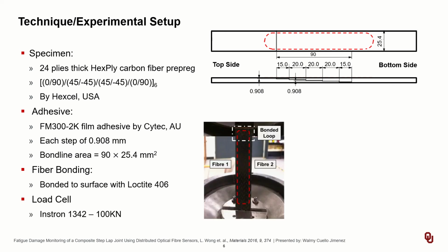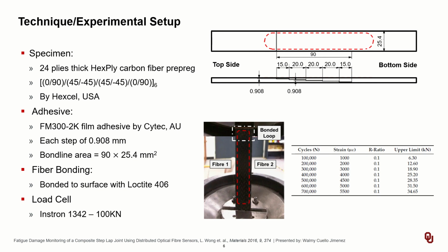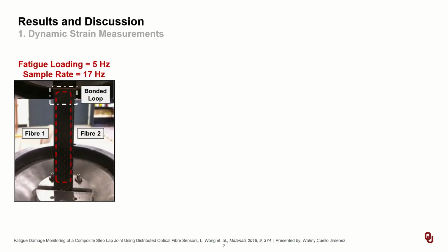component. And finally, the specimen is placed into a load cell with a capacity of 100 kilonewtons to perform the fatigue testing. As you can infer from the setup, the photo of the fiber was split into fiber 1 on the left and fiber 2 on the right for experimental purposes mainly. Now the fatigue testing is designed to increase by 1000 microstrain every 100,000 cycles with a minimum to maximum stress ratio of 0.1 throughout the entire experimental evaluation.